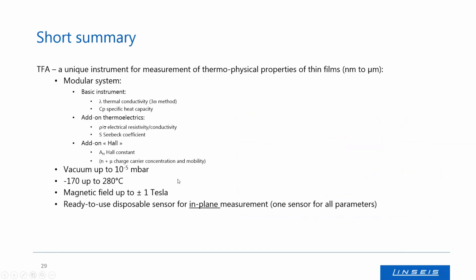So let's summarize. I showed the thin film analyzer, which is an instrument for the measurement of thermophysical properties of thin films. Thin films can have a thickness in the range of nanometers to micrometers. The thin film analyzer is a modular system with a basic instrument for the thermal parameters, conductivity and heat capacity. And there are add-ons, an add-on for thermoelectrics, for the electric resistivity and the Seebeck coefficient. There is a Hall add-on to measure the Hall constant and to calculate charge carrier concentration and mobility from this Hall constant. Measurements are usually performed under vacuum.